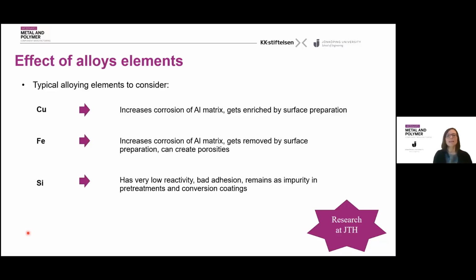Iron, on the other side, also increases the corrosion of the aluminum matrix, but can be removed by proper preparation. If we don't remove it, it can create porosity. And even when we remove it, we have to be really careful, because when we remove the entire particle containing iron, we may leave behind a void. If that is not well designed, it can create porosities.